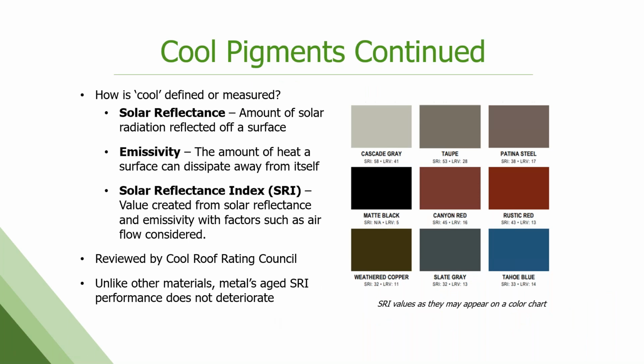So how is cool measured? There is a lot of terminology out there that can get a little confusing at times. So we have solar reflectance, that's the amount of solar radiation reflected off of a surface. We have emissivity, the amount of heat a surface can dissipate away from itself. Take those two values, do a big old gnarly calculation, and get the solar reflective index value, or SRI value, which is what we see in the specs a lot now. And there's an airflow consideration with that. Again, reviewed by the Cool Roof Rating Council as a third party.